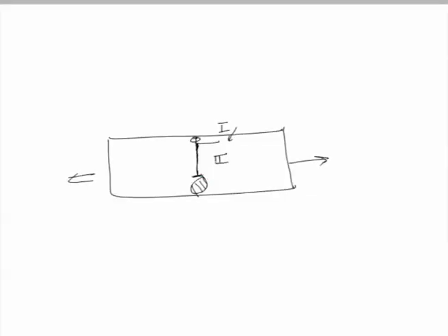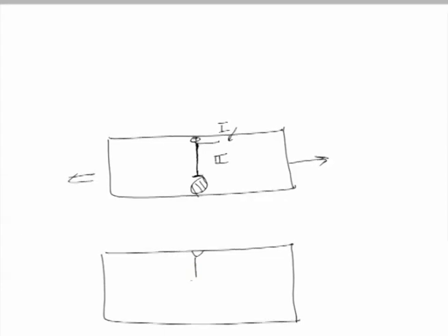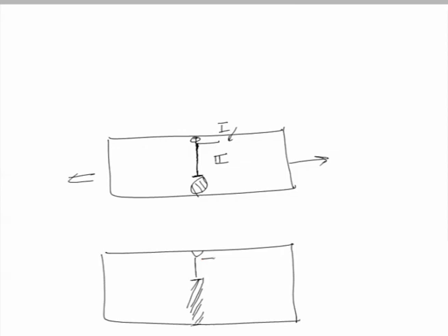Those metal systems which are very fracture tough will allow the crack to grow to a greater extent, while the materials which are not very fracture tough, after the nucleation stage and propagation of the crack to a limited extent, can undergo sudden fracture. So, even when a lot of load resisting cross sectional area is left for stage 3, sudden fracture can take place earlier. In that case the growth of the crack in the second stage will be very limited as compared to the first case, when the fracture toughness of the material was high.